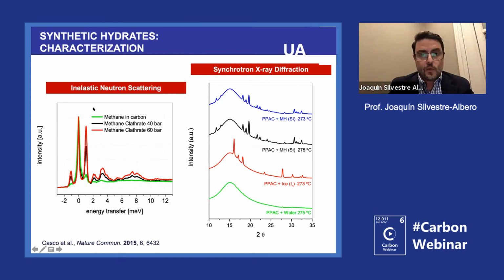With inelastic neutron scattering, what we observe is that when you have the carbon with methane, all the methane molecules start rotating, and at the end, the signal disappears because there is an overlapping in between all the molecules. And that's why in the green spectrum, we had the elastic peak at zero millielectron volts. And then there is a very tiny peak at 1 millielectron volts, but extremely narrow. So this is because, as I said, the methane molecules are rotating, but they are overlapping with each other, and then at the end, you don't get any signal.